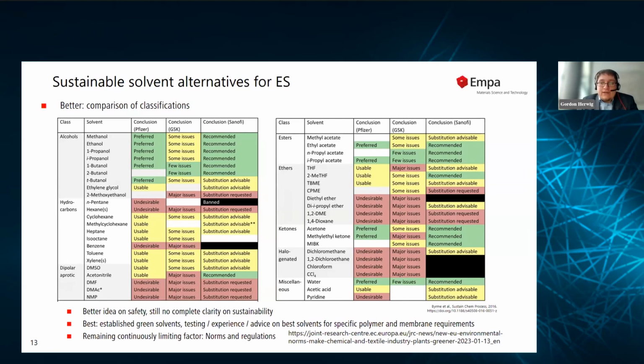Problem is, it doesn't tell you anything of how well soluble it is. So often we found out that the solubility for electrospinning is too narrow. For example, after adding, I don't know, 5 weight%, it already crashed out of solution. And that means it might actually form colloids or whatever there is. It's not ideal for electrospinning. Doesn't mean it doesn't work necessarily, but probably for industrial applications, it's not suitable because it's not scalable. So again, better switch to something that you have experience with or that's already mentioned in academia to work. And again, that's what we are working on, to be some sort of advisor that can help with this selection process.